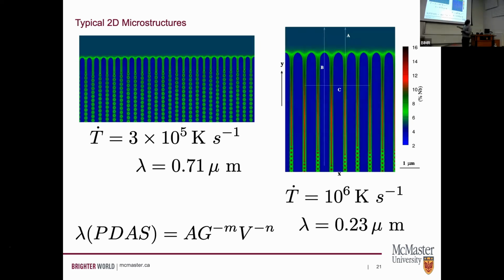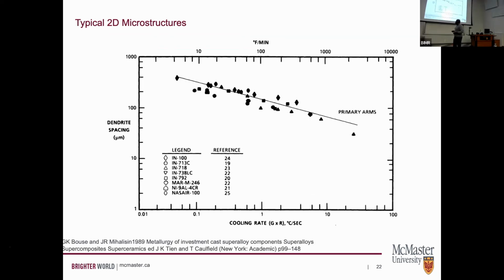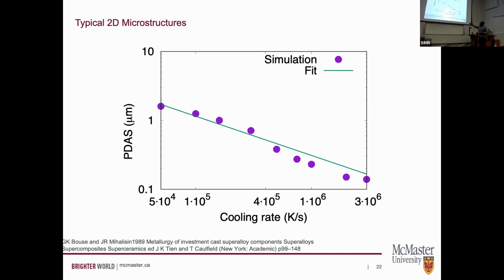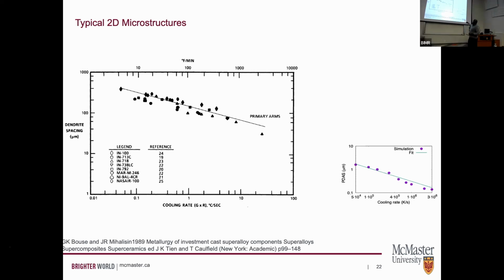And then what we're going to try to compare it to is this geometrical model that is somewhat well accepted in the literature in other casting and manufacturing, where you can define solidification. Okay. So we find that at 2 different cooling rates, we get 2 different patterns that form, as can be expected. The temperature is affecting how fast these things grow and what happens. And so we want to compare it to some experiments. So we found this in the literature that measured this spacing, this dendritic spacing, as a function of cooling rate with a similar alloy that we have. And then where our simulation fits is somewhere over here.